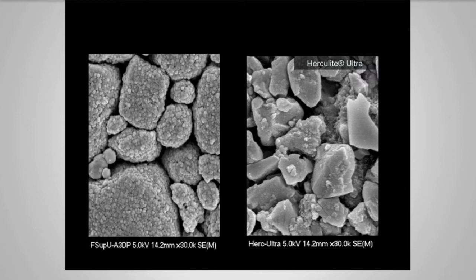On the left of the screen, you can see an SEM of Filtek Supreme Ultra, which is their current nanocomposite. And the particle formation is very different. Nanoparticles are very small little balls, and then they're clustered together in these clusters called nanoclusters. And the difference really is in the size. Typically, on a typical hybrid, you might have particle sizes even up to 1 micron. With nanocomposites, and not just 3M, but most of the nanocomposites on the market, you're going to see particle sizes in the 1/1000 micron range, which is really wonderful.